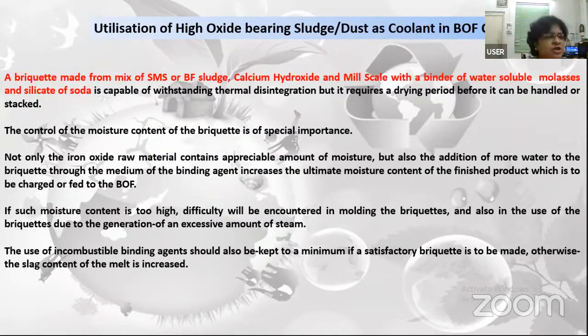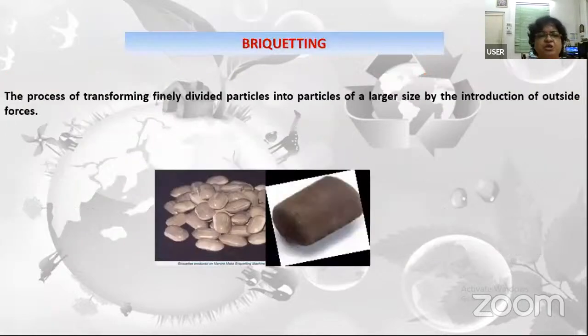The control of moisture content is of special importance. Not only does the iron oxide raw material contain an appreciable amount of moisture, but the addition of more water to the briquette through the medium of the binding agent increases the ultimate moisture content of the finished product, which is to be charged or fed to the BOF. So you have to take special precautionary measures in the metallurgical process for formation of the briquette.